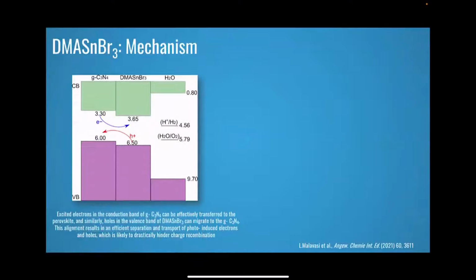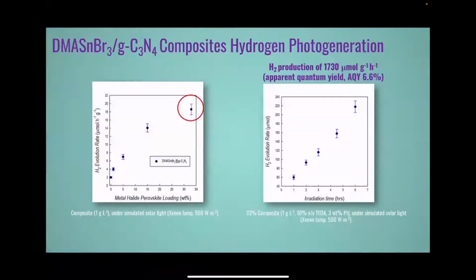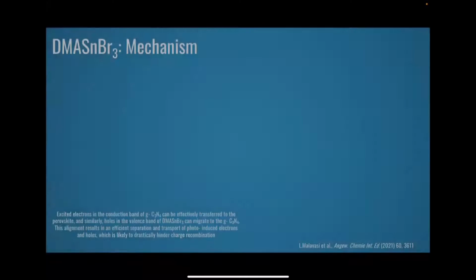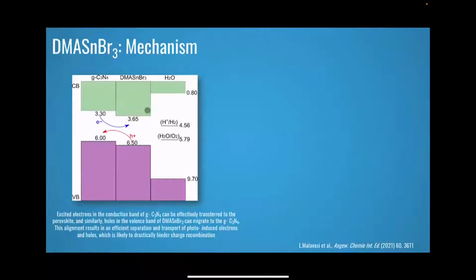We also investigated the mechanism. The basic idea is that there is a transfer of charge carriers between the perovskite and the graphitic carbon nitride. So we effectively create a heterojunction because, of course, here we achieve something like this value, but the graphitic carbon nitride alone gives a very low amount of hydrogen, and also the perovskite alone is quite low. So we have a synergy between the two. So we effectively created a heterojunction that improves significantly the hydrogen photogeneration reaction.